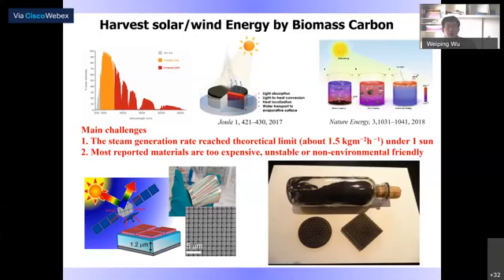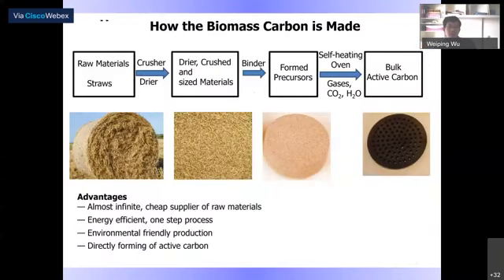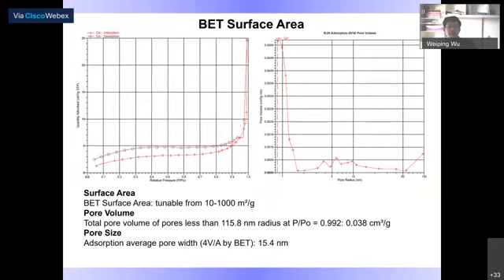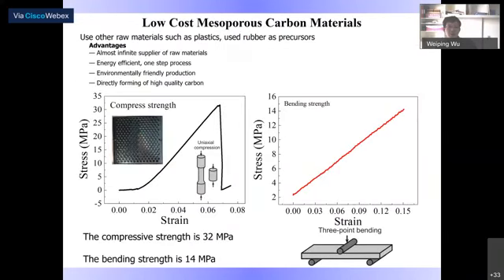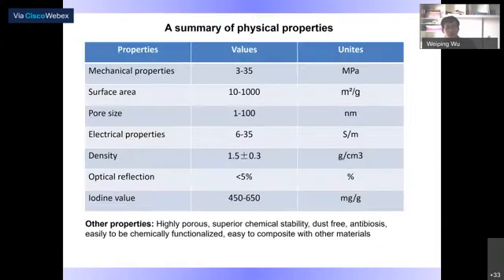So therefore, I propose using biomass straw to derive the carbon material as the active material for solar energy harvesting applications. This material has a high surface area and proper pore size. In addition, it has excellent mechanical properties. It's not just a powder. You get a bulk, very low density material, like a brick. So it's very lightweight, but it looks like small pieces of brick shape. So it allows us to construct solar steam generation devices.